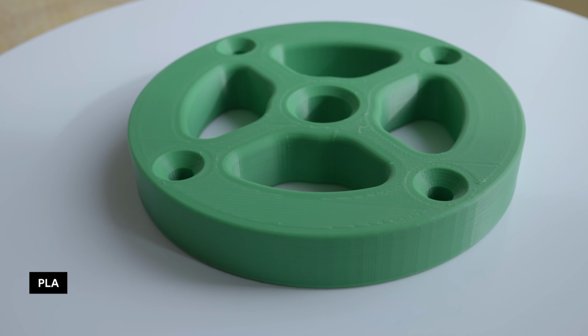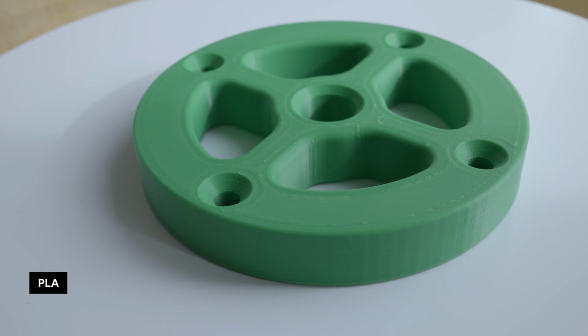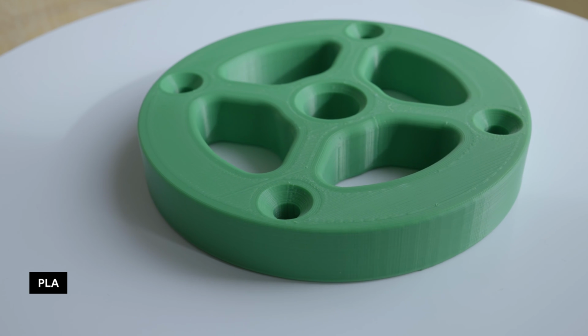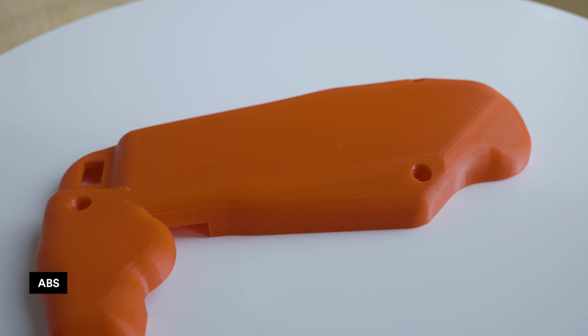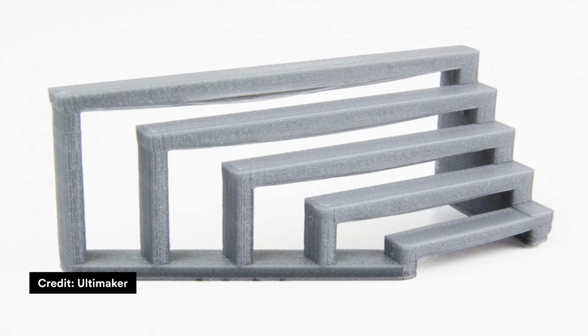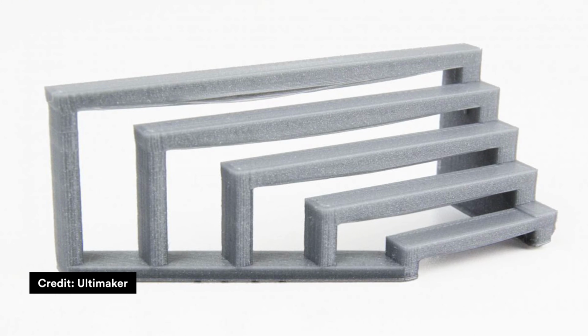Finally, it's good to mention that both can be printed at 100 micron layer height. PLA can handle complex features a little bit better, as vertical overhang can be done to 68 degrees, while ABS can only do 45 degrees. These values are most common, but with some tweaking, you might be able to push them. Finally, mid-air connections or bridges can also be printed better with PLA.